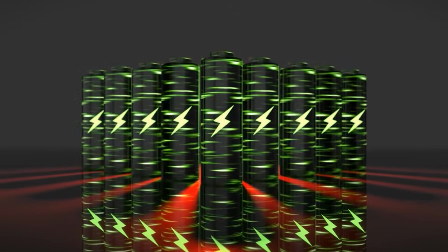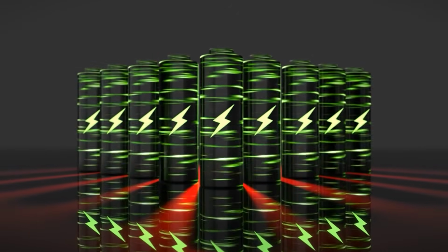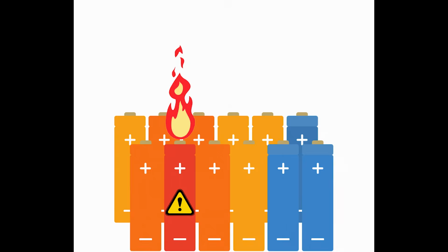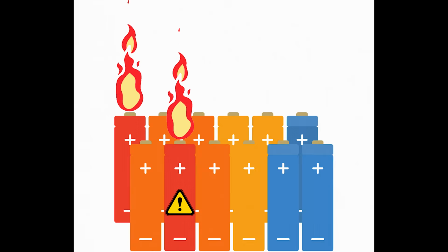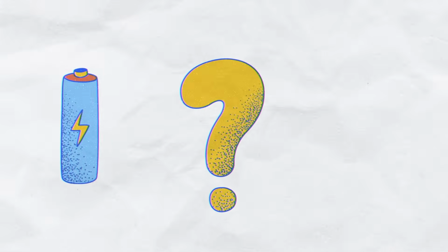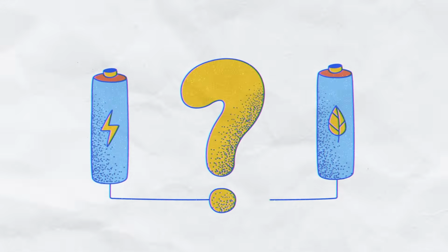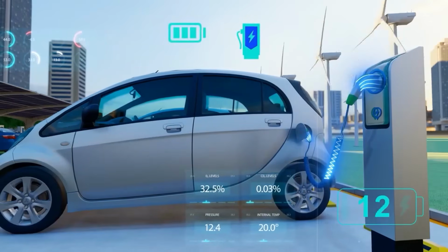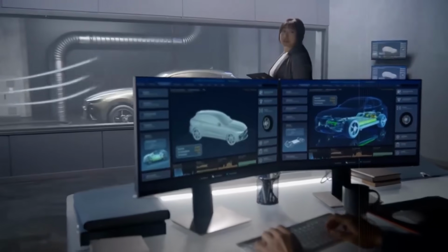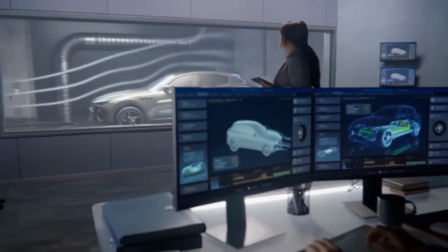spike past 1,000 degrees Fahrenheit in seconds. One cell in thermal runaway heats the adjacent cell past its critical threshold, triggering a chain reaction that can consume an entire pack. These fires burn with extreme intensity and can reignite hours after apparent suppression.